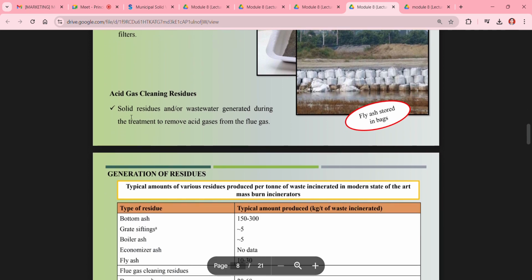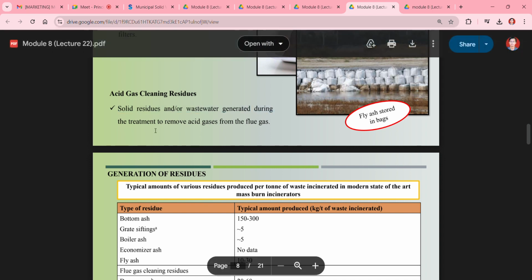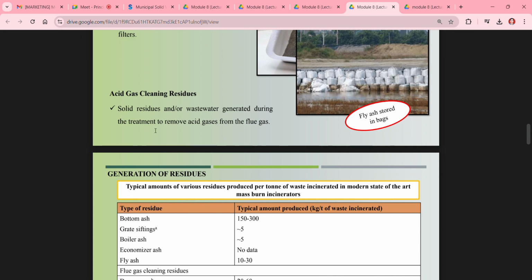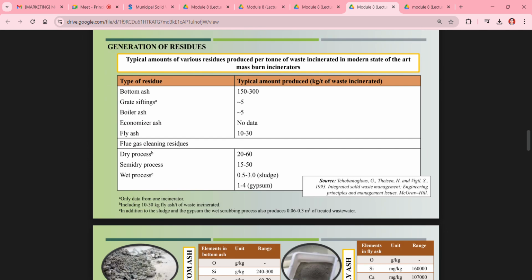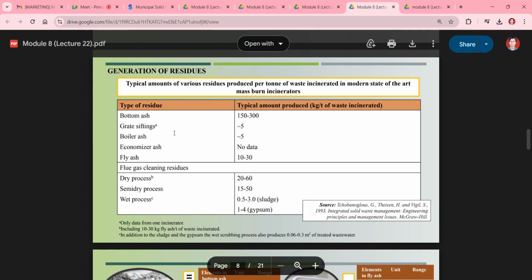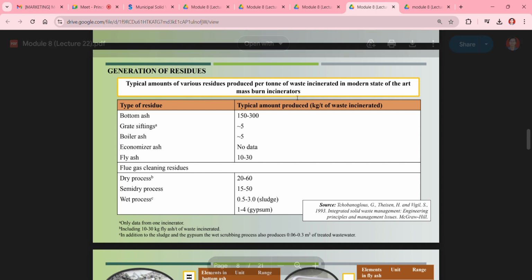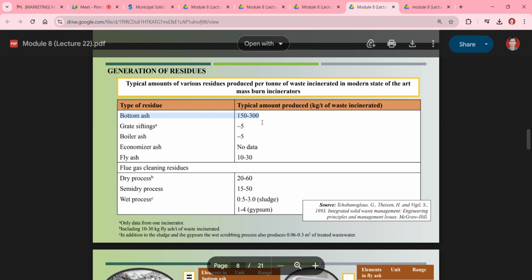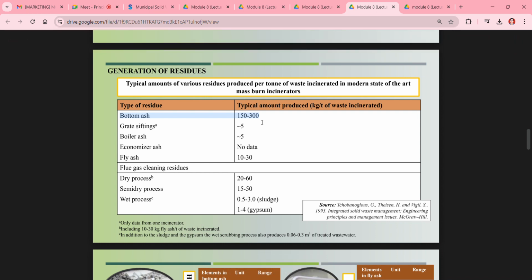Then coming to acid gas cleaning residue, the solid residue and or waste water generated during the treatment to remove acid gases from the flue gases is known as acid gas cleaning residue. So the typical amounts of various residues produced per ton of waste incinerated in modern state of the art mass burn incinerators generally contain 150 to 300 kg per ton of bottom ash. Then grate siftings can be around 5 kg per ton, boiler ash 5 kg per ton, and fly ash generated can be around 10 to 30 kg per ton.